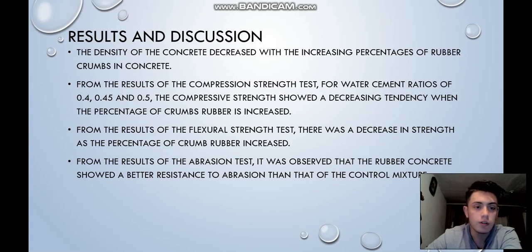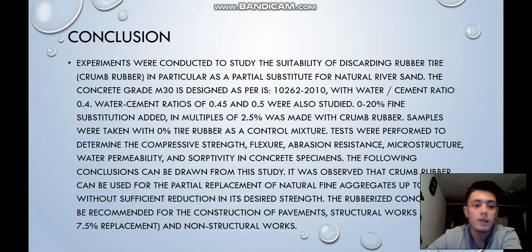Results and discussion. The density of the concrete decreased with the increasing percentage of rubber crumbs in concrete. From the results of the flexural strength test, there was a decrease in strength as the percentage of rubber increased. From the results of the abrasion test, it was observed that the rubber concrete showed better resistance to abrasion than the control mixture. Conclusion.